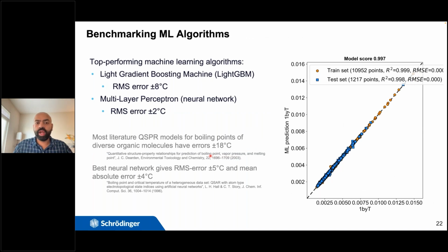So we trained a wide variety of algorithms to predict 1 over temperature as a function of pressure and chemical descriptors. And for example, the light gradient boosting machine has a root mean square error of around plus or minus 8 degrees Celsius. But our multi-layer perceptron was extremely accurate in predicting the boiling point, and the error was around plus or minus 2 degrees Celsius. And these two gray areas show some other data sets available in literature and some other publications. And from what we observe, this is really the best performing model for boiling point for such a huge chemical space that exists in literature.